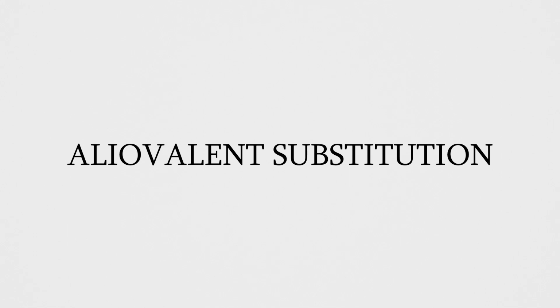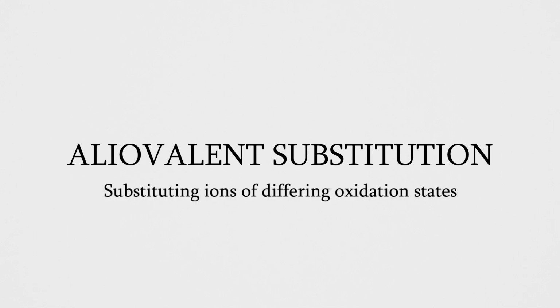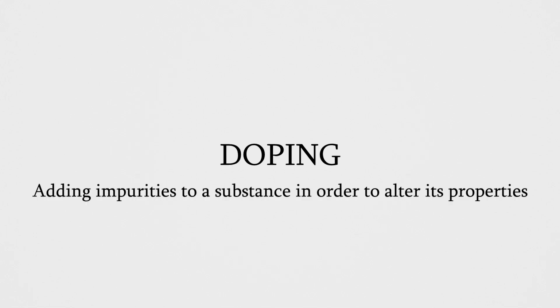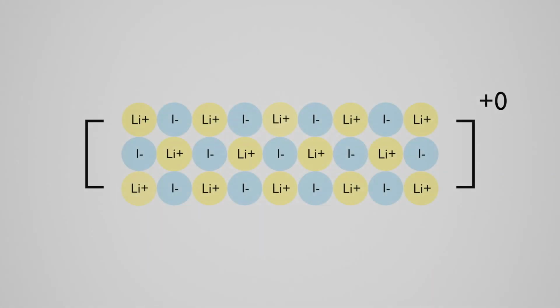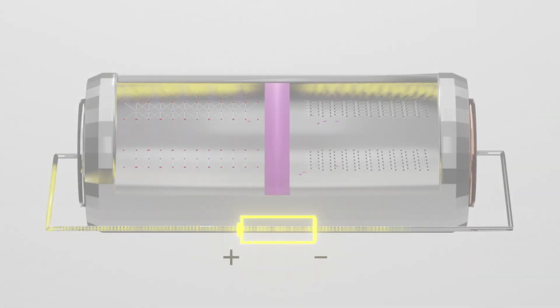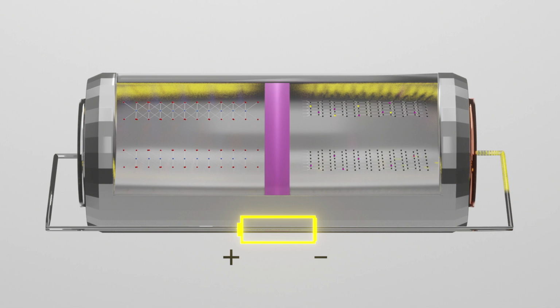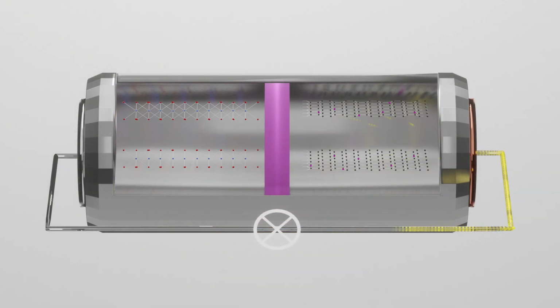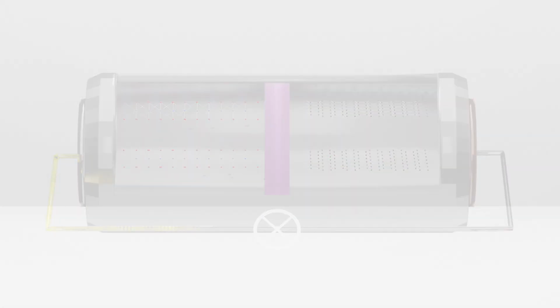Aliovalent substitution involves integrating ions with greater individual charges into the crystal in order to balance the charge. This can be carried out via doping. For instance, we could create vacancies in a lithium iodide crystal and then balance the charge with half the number of doped magnesium ions, leaving a free vacancy for every magnesium ion, thereby allowing lithium ions to diffuse through the crystal.